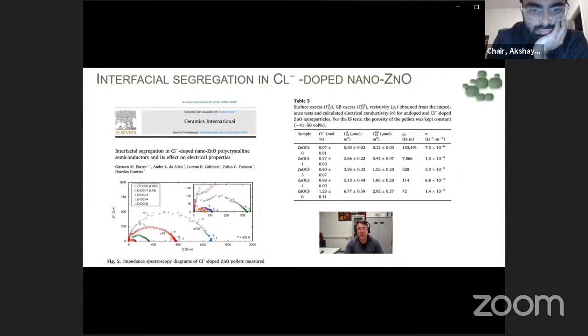In this slide, you can see the chloride segregation results on zinc oxide nanoparticle surface. These results were recently published in Ceramics International, and I invite you to read this paper, and showed that there was an intense chloride segregation on the surface, but at the same time there was segregation at the grain boundary. The segregation at the grain boundary causes a destruction of an electrical potential barrier. It is well known in the manufacture of zinc oxide varistors, and this destruction of potential barrier at the grain boundary causes an increase in the conductivity.